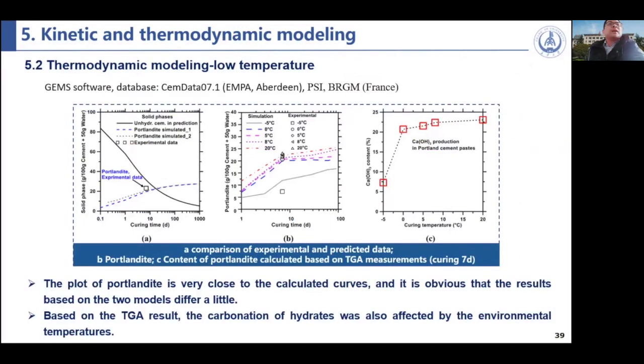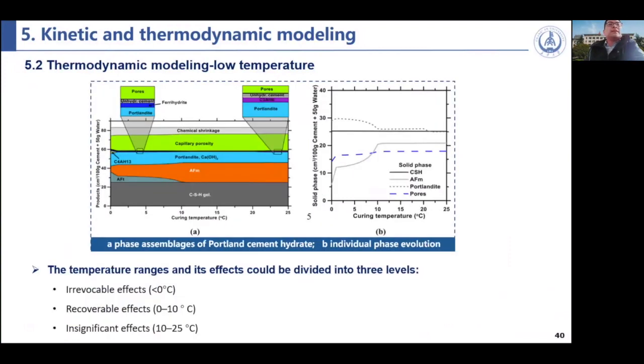We also use GEMS to do some thermodynamic modeling under the lower temperature and the low pressure. The database we use is the cement database developed by EMPA and University of Aberdeen, and also PSI, and Gibbs energy minimization is also used in our research. We can see this point and this point are what we got from the experiment, and these are calculated. It proves that our calculation and the experiment data are in good agreement, and we also got the hydrates during the lower cooling pressure and the lower cooling temperature.